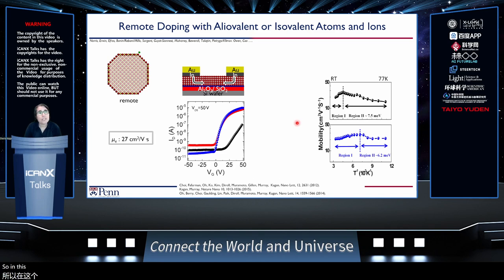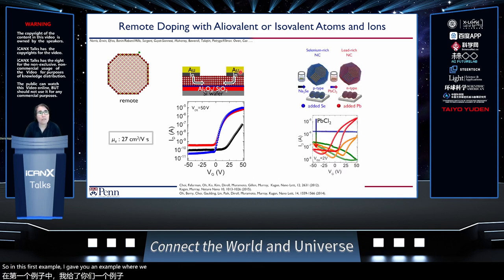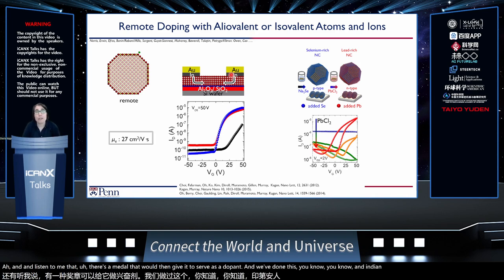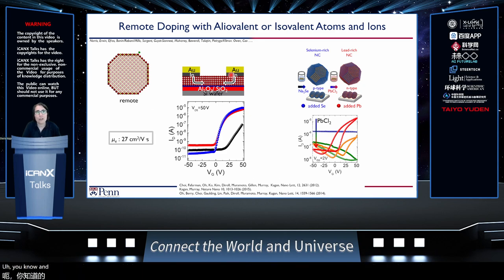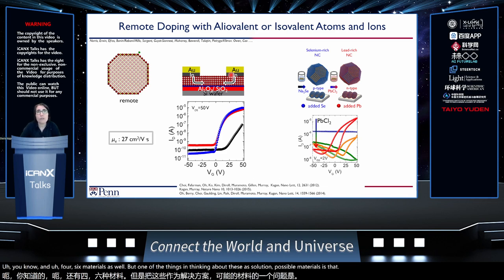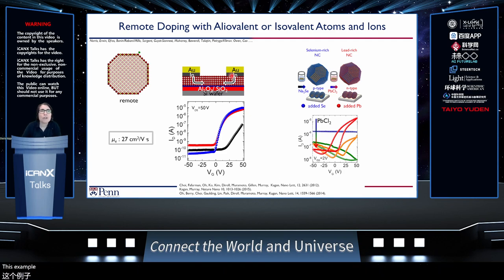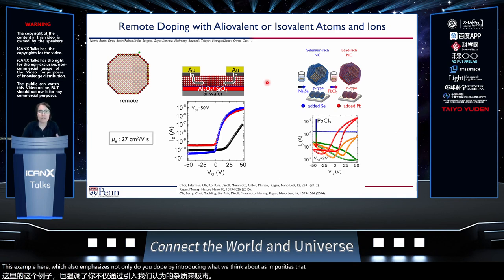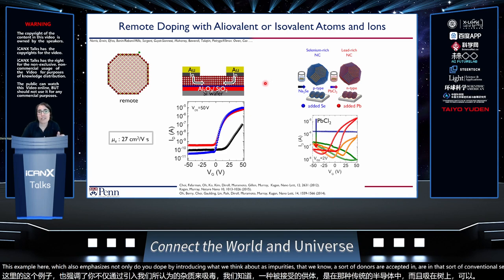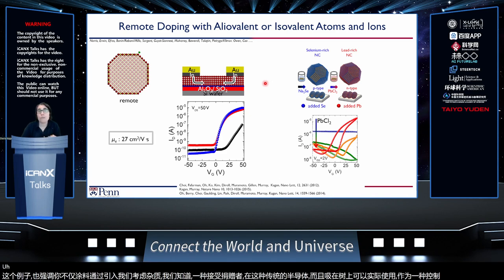So in this first example, I gave you an example where we evaporated a metal that would then serve as a dopant. And we've done this beyond indium for other metals as well, in II-VI materials as well. But in thinking about these as solution processable materials, we also wanted to develop a solution process by which we could dope these materials. So I thought I would choose this example, which emphasizes that not only do you dope by introducing what we think about as impurities, the donors or acceptors in our studies of conventional semiconductors, but stoichiometry can also be used as a way to control the doping concentration.